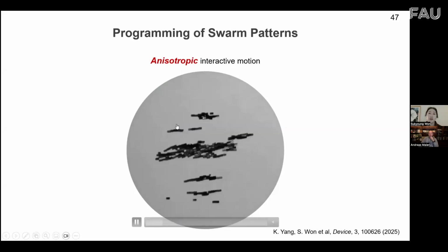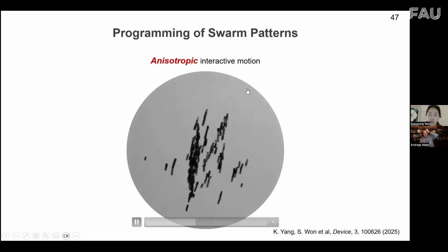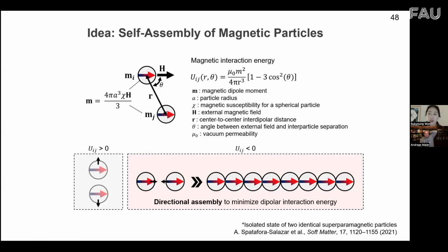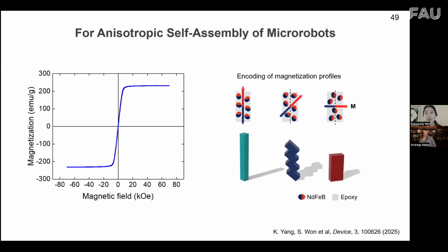The anisotropic interactive motions can be inspired by the self-assembly of magnetic particles. When we see the magnetic interaction energy, these magnetic particles assemble directionally, with the direction of the chain along the external magnetic field. Even without the magnetic field, what if we control the magnetization inside the robot body?